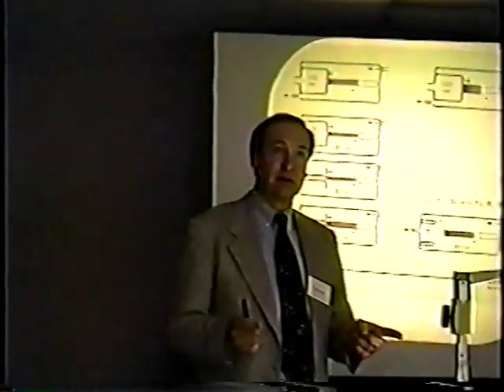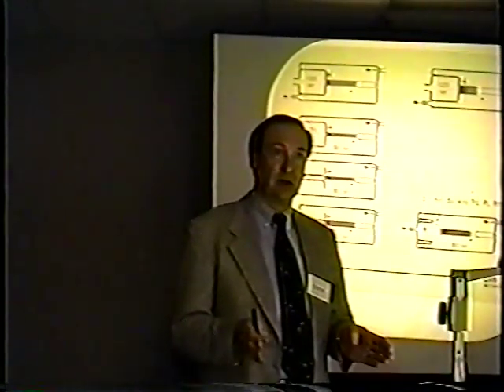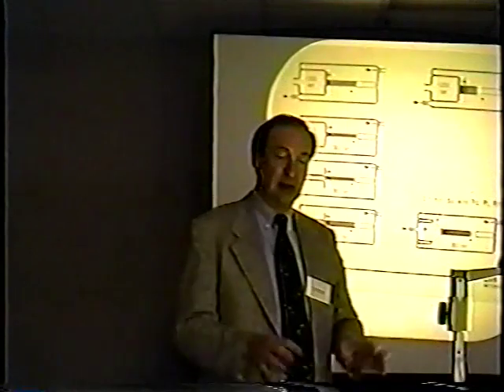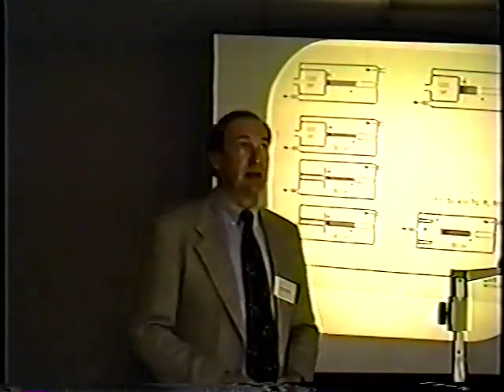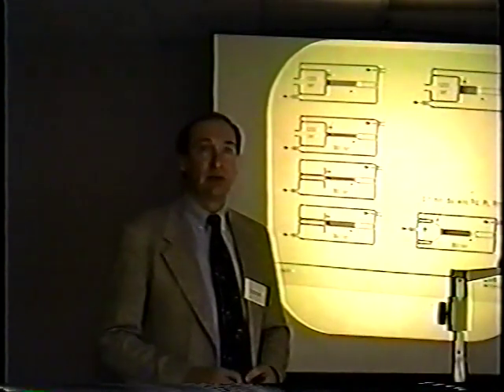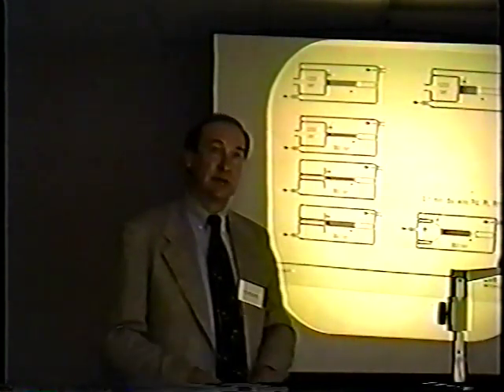Good job. You claim that stress relief reduces tritium production. Do you have a quantitative estimate? What kind of residual deformation do you have when you see it? What we've done is on the Goodfellow wire, we've stress relieved it by heating it at 600 for maybe an hour, so it goes limp. And there's maybe a 3 times reduction in the tritium output, but it doesn't go to zero.